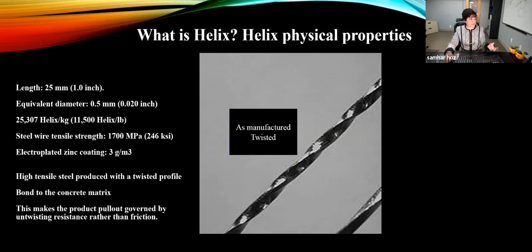This allows the product as a high tensile steel product with a twisted profile as shown here. This is Helix as manufactured. Those twists allows the product to bond well to the concrete and makes the product pull out governed by an untwisting resistant rather than just friction.